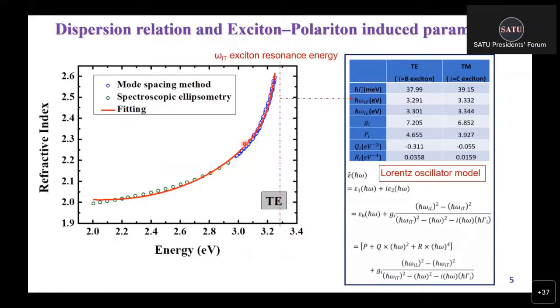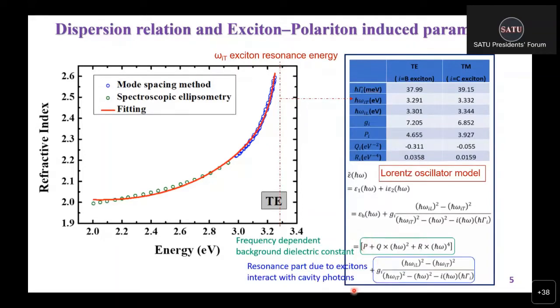You can see clearly that the index dispersion increases gradually when the energy approaches about 3.3 eV. This is because the energy is very close to the semiconductor exciton resonance energy. In order to obtain the index dispersion in a wider energy region, we also consulted ellipsometry data from other groups, which are the green circles here. Combining these two parts and applying the Lorentz oscillator model, we can fit the index dispersion as the red lines here in a wider energy region.